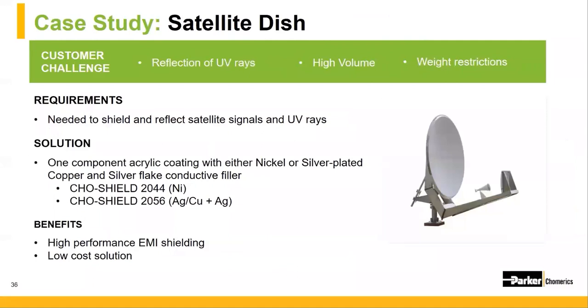Expanding into other industries, we've actually worked on several satellite dish applications for customers in defense, aerospace, and telecommunications market segments. In this particular application for a commercial satellite dish, the coating would be applied in high volume to provide incident electromagnetic interference protection and would need to withstand long-term UV radiation exposure all over the globe. So an acrylic-based coating with a nickel filler actually met all of the electrical properties. And because it was a high volume application and because of the environmental exposure, it was combined with a UV radiation protective top coat.